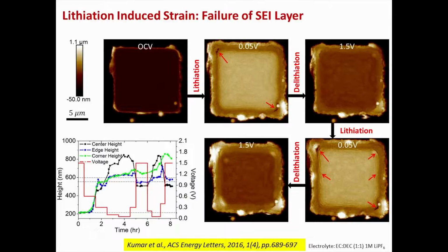So I'll talk about some of the results that I get. Most of my silicon islands are almost 200 nanometers thick and 15 by 15 micrometers in dimensions. As I'm going through lithiation, there is a significant amount of expansion both laterally and vertically. Most of the expansion is vertical, but there is a lateral expansion of these electrodes at the edges of these islands. Because of that, you start seeing some kind of cracking appearing in these edge and corner zones. I'll talk later about why it is happening mostly in these corner and edge zones.